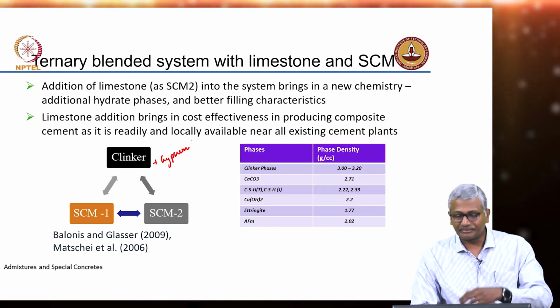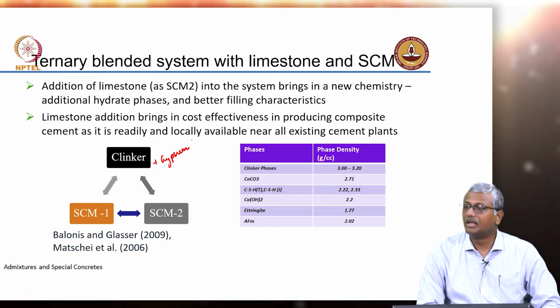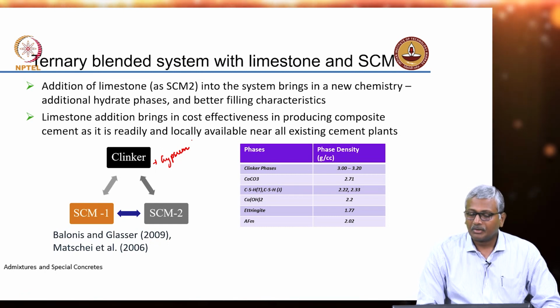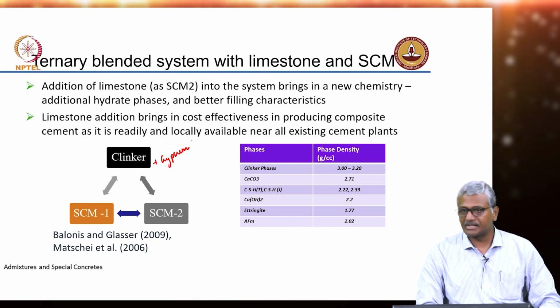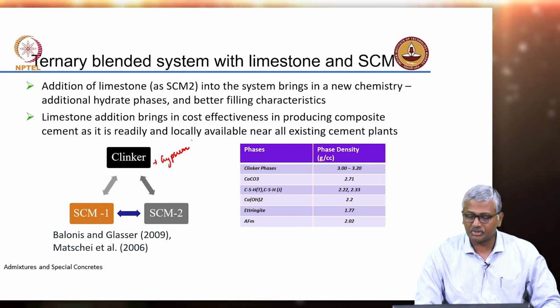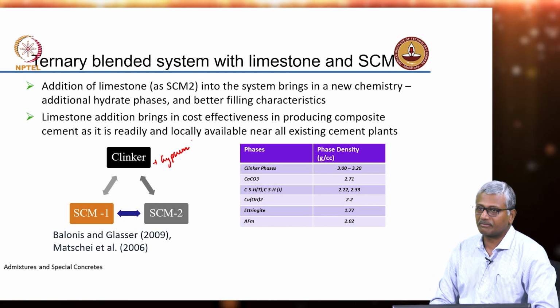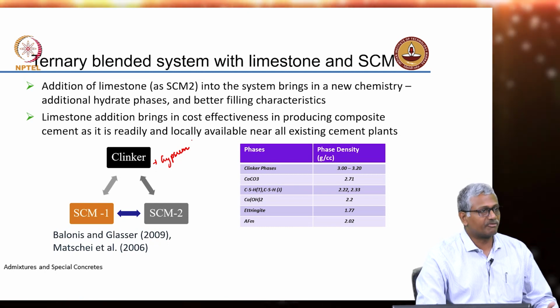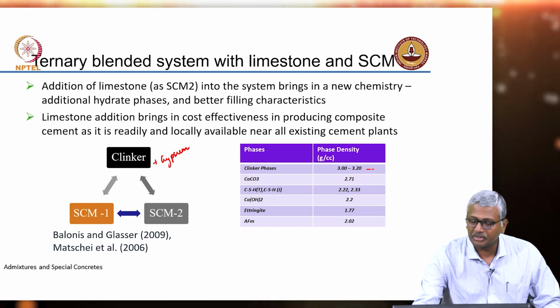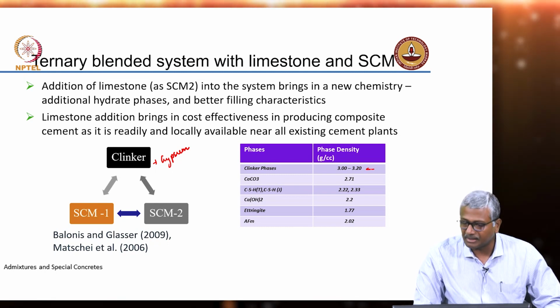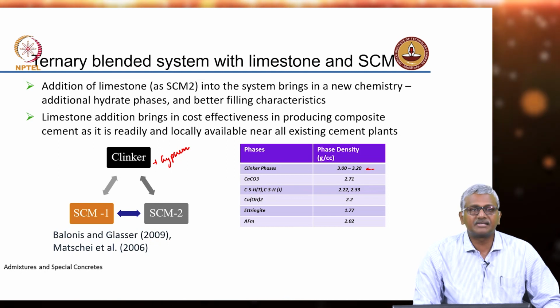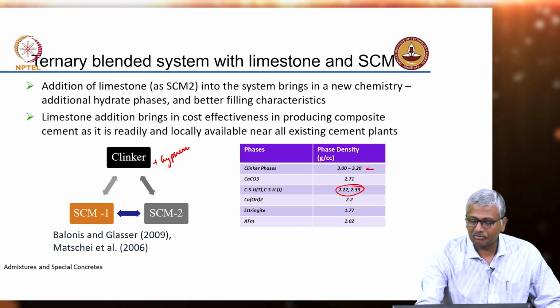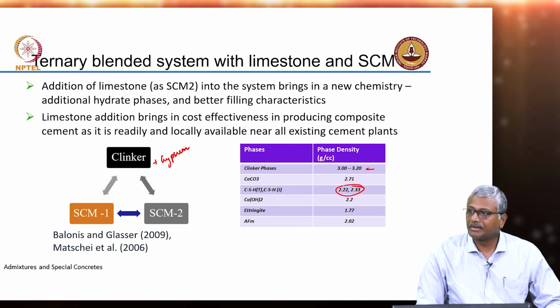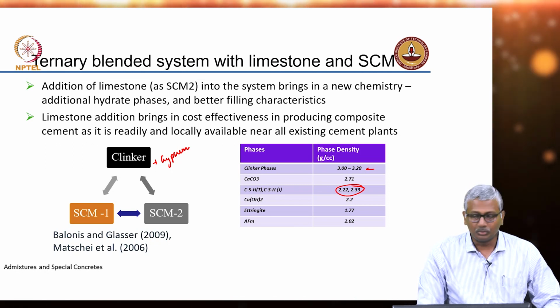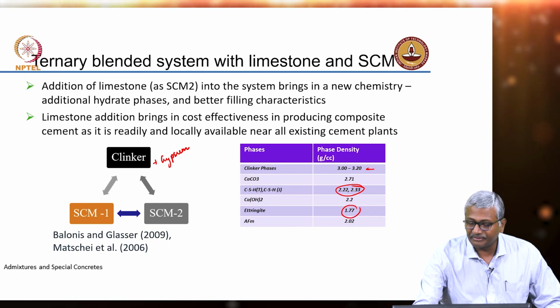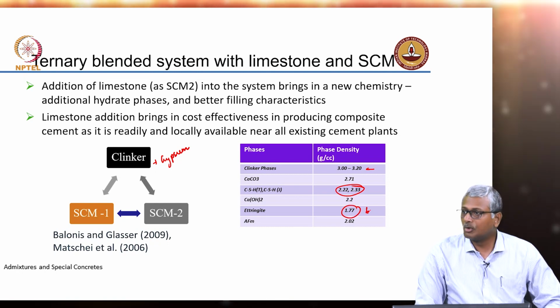So what you end up doing is, let's say these are the phases that you form when cement hydrates, right? When cement containing some limestone in itself hydrates, these are the phases that are actually present, and the densities of those phases are also given here. We know the density of cement is about 3.15. So most cement phases are in the same range of density. Unhydrated cement will have that level of density. But when you hydrate, the CSH that you produce gets a density of about 2.2 or 2.3. Calcium hydroxide is almost the same, 2.2. But interestingly, if you look at the ettringite phase, density is lower.